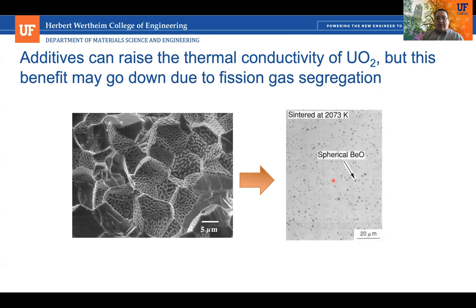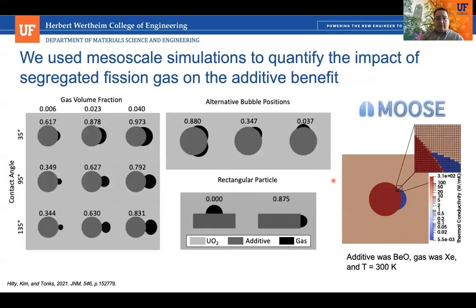And so we're going to start concentrating fission gas around these particles. And we can imagine that's going to significantly impact the thermal conductivity, and we might start to lose the benefit of these high thermal conductivity additives. So we wanted to explore that, and we're exploring it using a fairly simple system. So we have a 2D system with a single additive particle.